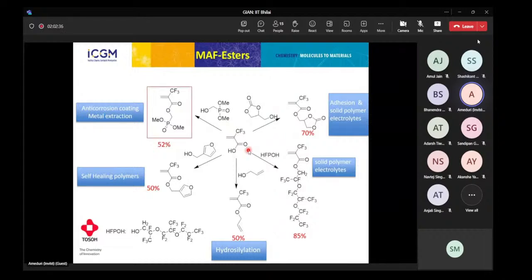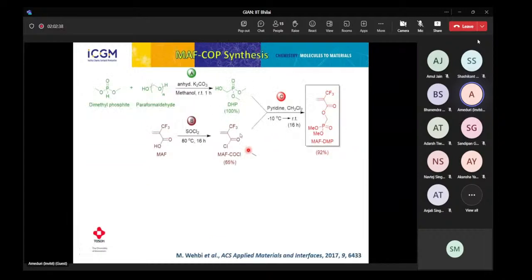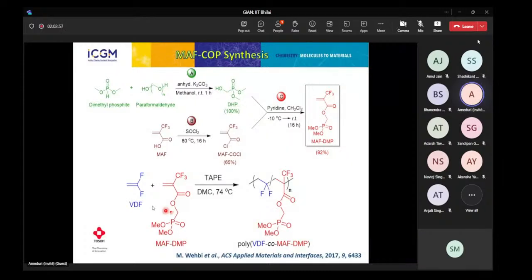So the first action was the synthesis of this monomer. It was possible to use dimethyl phosphite with formaldehyde to make this primary alcohol, and then the acid chloride could react, condense with this primary alcohol to lead to that. It was good. And then this was copolymerized with VDF in order to prepare some PVDF containing phosphorus.